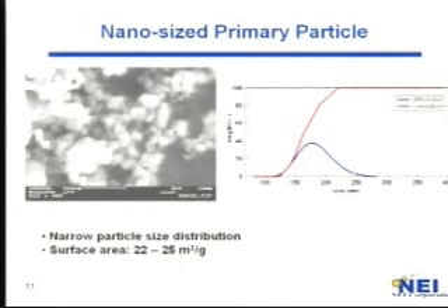Because I wanted to show here, as I said in the beginning, there are two types of material one can make. One where you have individual nanoparticles, and another where you have nanodomains. So lithium iron phosphate is the case where you have individual nanoparticles. Again, you can see that this is a field emission scanning electron microscope image, and each particulate is around 100 nanometers. On average, of course, there is a size distribution, and then there is the aggregate size.